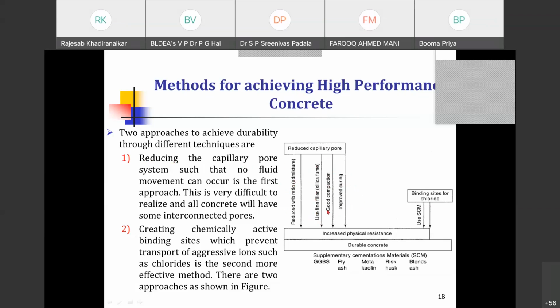So reduced water binder ratio, use of filler materials like silica fume, fly ash, GGBS, rice husk ash, and other similar materials, and go for good compaction and improved curing. If you take these precautions, then there will be an increased physical resistance. The capillary pore system will be reduced, and automatically there will be an increased physical resistance. And if there is increased physical resistance, automatically you will be able to produce a durable concrete. That is one technique, that you reduce the capillary pore system.